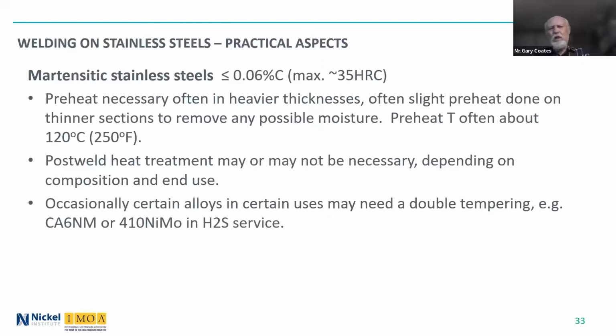You usually use preheat on heavier thicknesses, slight preheat maybe on thinner sections, mostly to make sure you remove any moisture from the surface, because they are sensitive to hydrogen that may form when you weld a wet or moist material. The preheat temperature is often relatively low, 120 degrees C. Post-weld heat treatment may or may not be necessary.